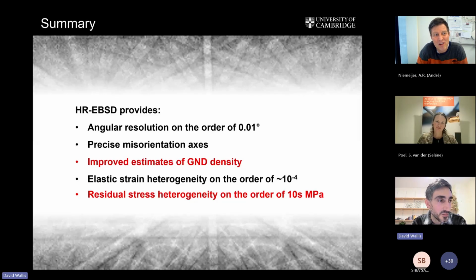I think it depends a lot on the material. For silicates and carbonates, if you go too small, you get limited by beam damage. Once you've mapped one row of the map, there'll be some damage underneath it and you start mapping into your own damage. For things like quartz and calcite, it's difficult to go below about 0.5 micron.